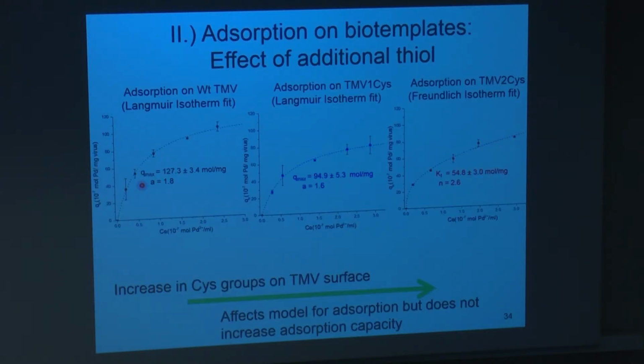So we looked at the adsorption of palladium on TMV, and this is the loading of material on TMV, 127.3 moles of palladium per kilogram of TMV. And you primarily get a Langmuir isotherm type of behavior, but in some cases you get a Freundlich isotherm effect.